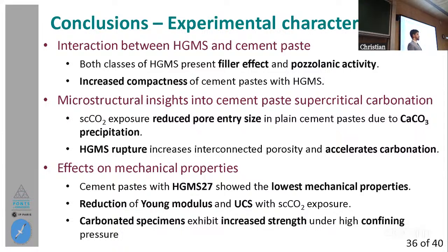In terms of microstructural characterization, we are able also to measure the influence of the exposure to CO2 injection and legacy wells conditions, which reduce the pore entry size peak that appear due to the calcium carbonate precipitation. And also we have seen that the rupture of the spheres affected a lot the advancement of this carbonation process. Also, this affected the mechanical properties.